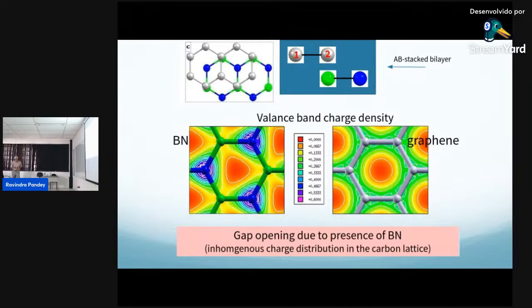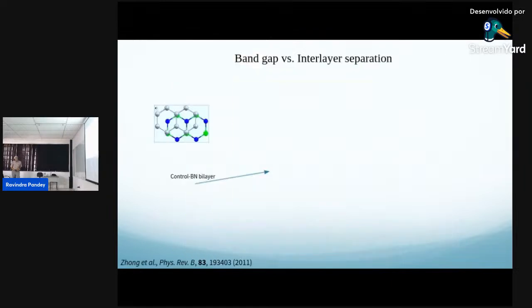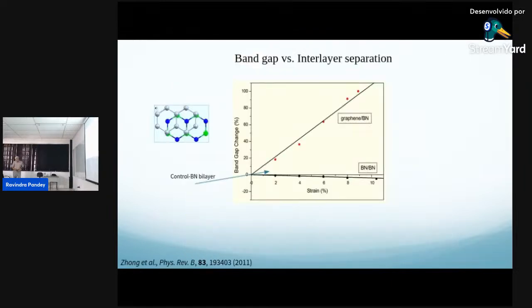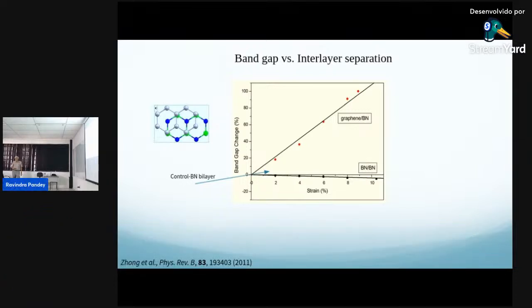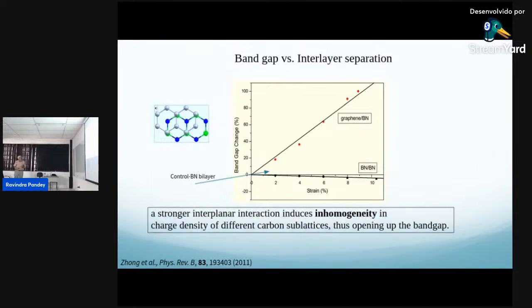This again is the experiment we always do. And so you can see here, this is our equilibrium structure. Now we are applying the strain, so reducing the distance. So these ions or atoms are interacting more and more. That should open up the gap. And that comes out very nicely: as we reduce the interlayer distance, the gap opens up. Now for the reference case, we do not expect it to open because of the boron nitride bilayer. You can see it remains flat. So that sort of proves that indeed there is an interplanar interaction which induces inhomogeneity in the charge density of this carbon sublattice, which opens the band.